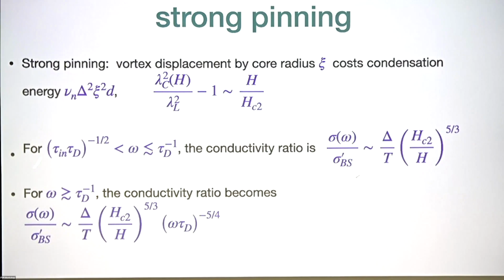At strong pinning, where you estimate the spring constant as the loss of condensation energy, again, this ratio of Campbell length to London length can be expressed in terms of the ratio of H over HC2. And then these expressions for the diffusive contribution simplify. And we see that at strong pinning, this far field contribution exceeds the Bardeen-Stephen contribution as long as the magnetic field is smaller than HC2. And then it decreases at higher frequencies.